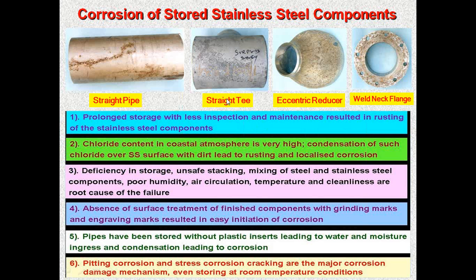It's very, very unusual. Chloride content in a coastal atmosphere is very high. Condensation of such chloride over the stainless steel surface, with dirt, leads to rusting and localized corrosion. Deficiency in storage, unsafe stacking, mixing of steel and stainless steel components, and poor humidity, air circulation, temperature and cleanliness are the root causes of the failure. Another cause was the absence of surface treatment of the finished components. You can see that some of the components, after they were finished, were not pickled or passivated. They were kept in the as-fabricated condition. That was one of the reasons.